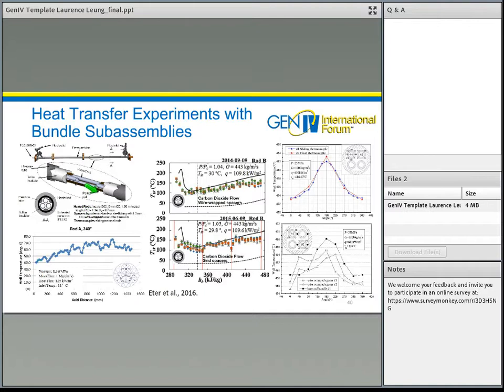In this case, they measured the 3-rod bundle in a carbon dioxide flow, and this is the axial wall temperature variation in one of the rods at different axial locations. They also compare the difference between the grid spacer and the wire spacer. Again, the wire spacer seems to provide a systematic improvement in heat transfer, or lower wall temperature, but the grid spacer introduces an improvement in heat transfer at the grid area, and the improvement decreases very fast downstream of the grid spacer.